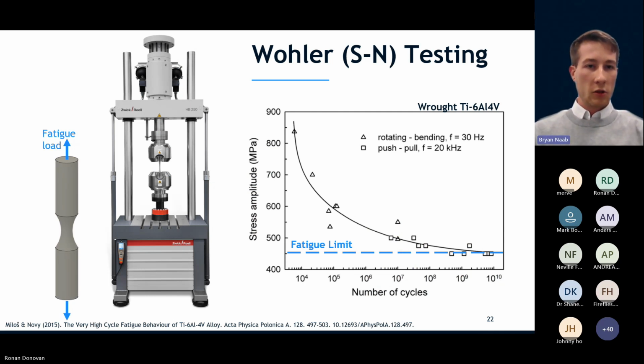So I want to touch upon the most important fatigue test, which is the Wohler or SN test. S stands for stress and N stands for number of cycles. The way that this test runs is we have a standard specimen and we apply a fatigue load, generally using a servo hydraulic test system, and we will decide on a maximum load, a maximum stress for that particular sample. We will test it under fatigue until it fails, and we will record the number of cycles which it survived.